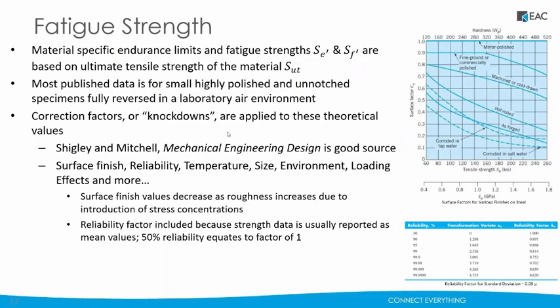I mentioned before that you can't necessarily start with an SN curve and then index stress right away. You have to apply these knockdowns. It would take quite a bit of time to go through each of these knockdowns, so we don't have that, but I wanted to put them on screen and talk about them briefly. For example, whether the specimen is machined, hot rolled, forged, corroded, polished. There are different ways to index, and depending upon this, you can index the tensile strength of that material, what your surface finish is like, and eventually come up with a correction factor.